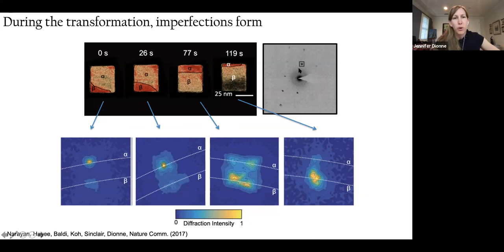We're zooming into one diffraction point, and you can see right at the beginning of the transformation, that diffraction point is actually 2 subpoints corresponding to the alpha and beta phase, depending upon whether you're looking at the inner or the outer ring. And you can see that the full width half max of this diffraction point is quite tight. So the particle is still a single crystal. As the transformation progresses, you can see that individual diffraction point actually broadens a bit, implying that various lattice imperfections are forming. Those could be various defects. They also could be just quite a bit of strain, coherent strain within the nanoparticle. But then amazingly, at the end of the transformation, once the hydrogen has moved across the entire nanoparticle, the full width half max of the diffraction point tightens up again.